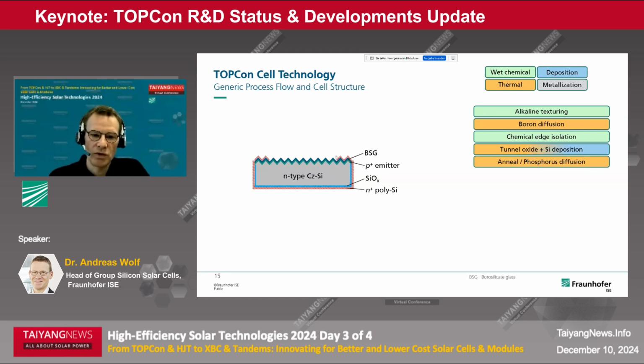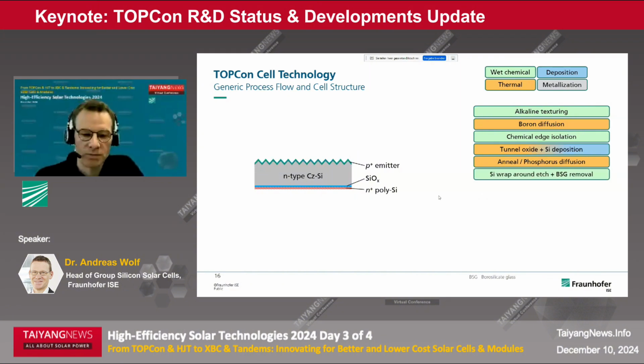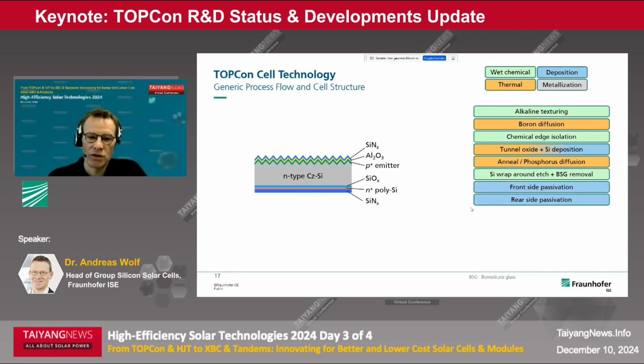This usually occurs with a wraparound as well. Might also be that the whole front side is covered by the layer, so you need to remove this wraparound in another wet chemical step. That also removes the BSG layer. And then the next step is the surface passivation.